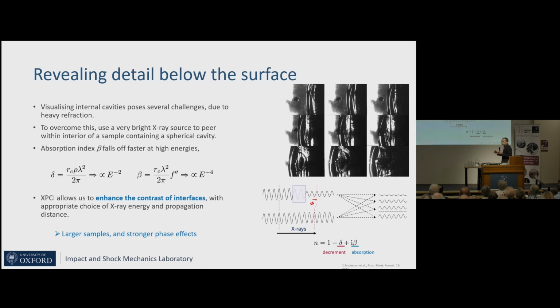If they're transparent liquids or certain plastics, then yes, we could look inside. But even if you do that, there's some recent work, and what you can see is this is a transparent material. You can see a shock wave driven from the right-hand side to the left. Here's the cavity, and you see very little detail inside that cavity, right? So there's very little that you can really glean from that interaction. So what we exploit then is we use different radiation. We use X-rays, and the particular technique that we use is known as phase contrast imaging.